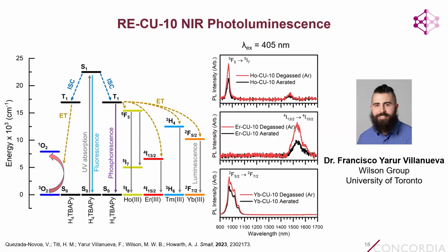We did not see any emission for the thulium analog, but this is to be expected since thulium is well known to undergo cross-relaxation processes. And in the crystal structure, we can see that those thulium ions are only 3.9 angstroms apart, which is well within the distance for cross-relaxation and quenching to occur.